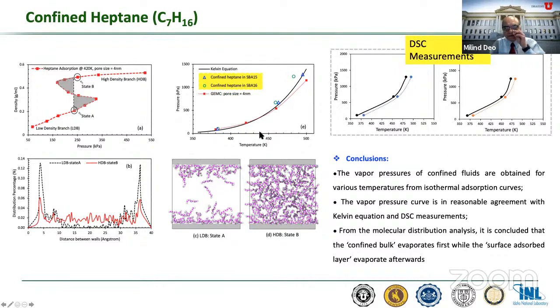So here are the experimental observations that we see for confined heptane and confined toluene in SBA 15 and 16. And the GEMC simulations more or less match that, but not quite. There are some deviations that we see. So again, in this particular study where the bulk actually surrounds the confined fluid, we do see a confined transition that occurs later than the bulk melting point, which corresponds, by the way, to a suppressed bubble point.